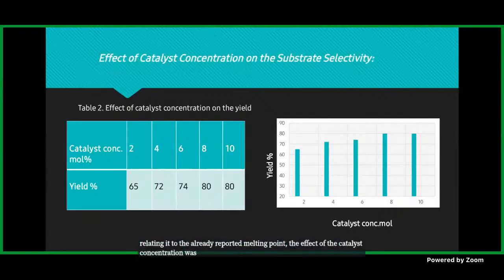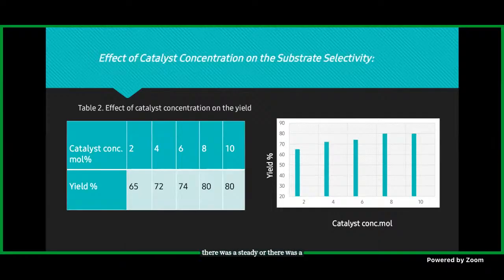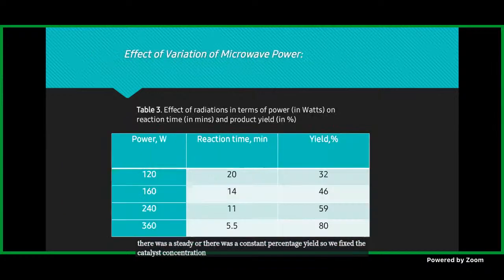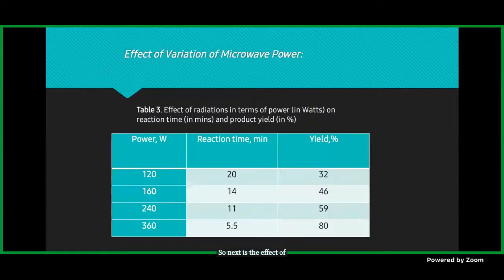The catalyst concentration was varied from 2% to 10%, and we found that there was a gradual increase in the yield up to a concentration of 8 mole percent. After that there was a constant percentage yield. So we fixed the catalyst concentration at 8%. Next is the effect of variation of the microwave power.